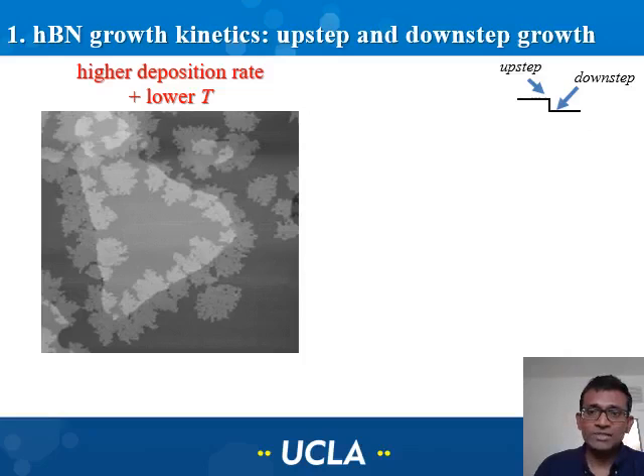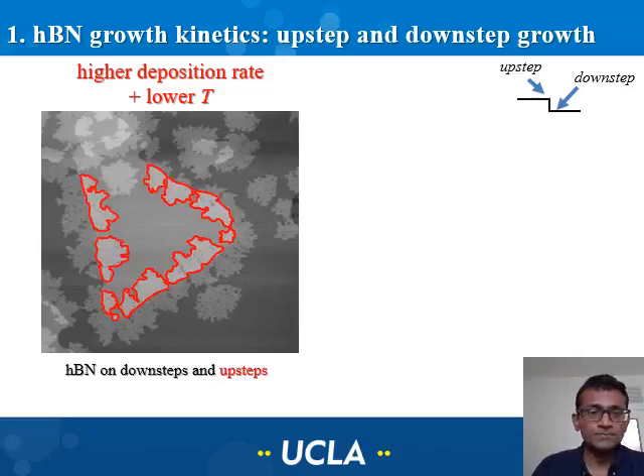If the deposition occurs here, I'm going to call it attachment at the down step. And if the deposition occurs here, then I'm going to be referring to that as the deposition at the up step. And as you can see here, there is hexagonal boron nitride attachment at the up steps and at the down steps.